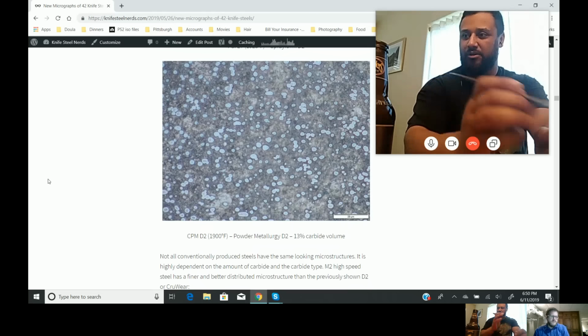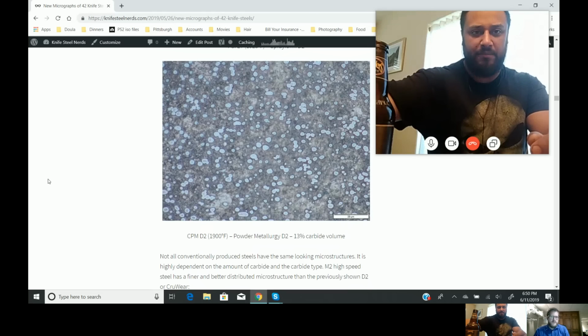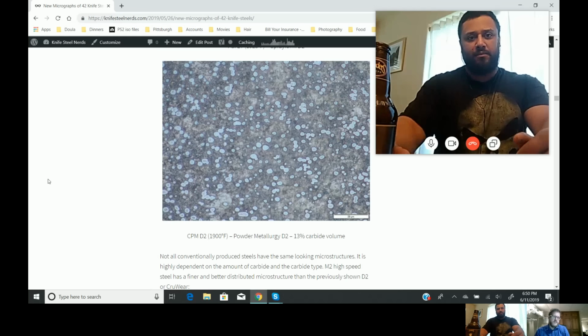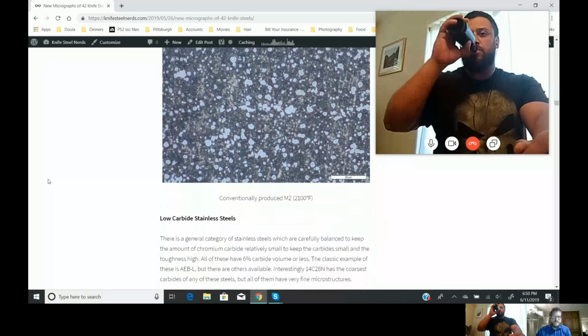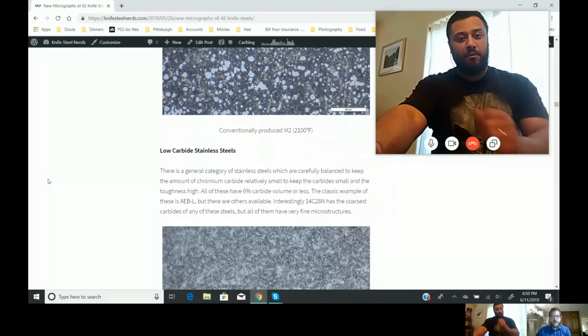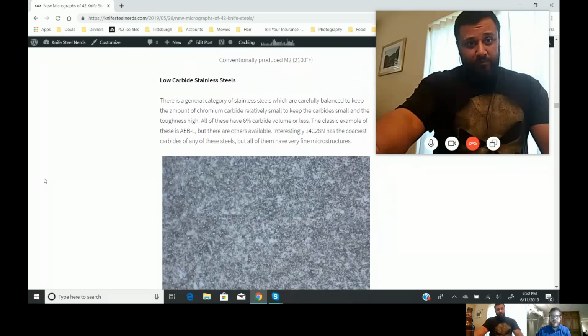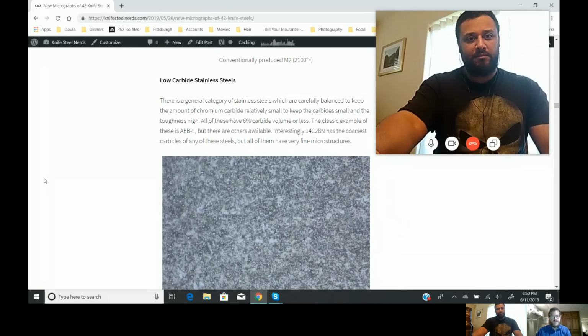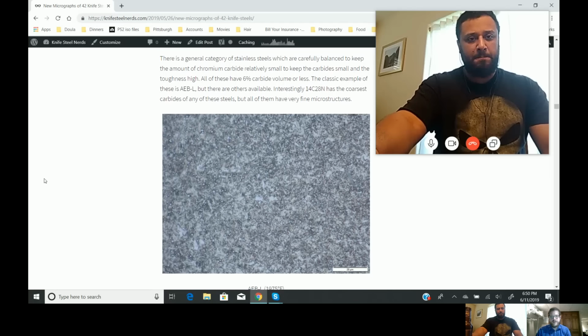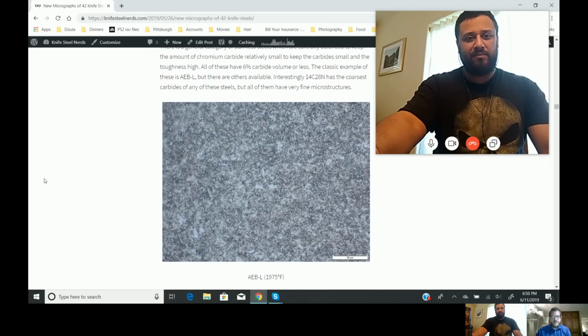I guess we can kind of conclude from all this micrograph stuff, huh? In powder metallurgy steels, chromium carbides are bigger than vanadium carbides, almost always. Okay, then the next category is low carbide stainless steels, and these are not powder metallurgy steels. But by controlling the carbon and chromium content, they make it so that you can dissolve and refine the carbides during forging and annealing. And so powder metallurgy likely wouldn't improve the properties of these steels.